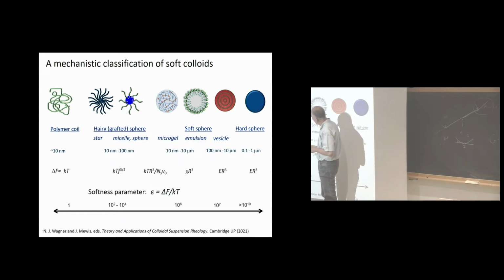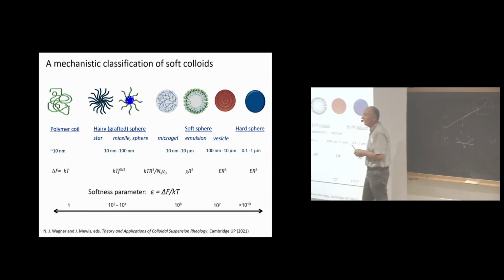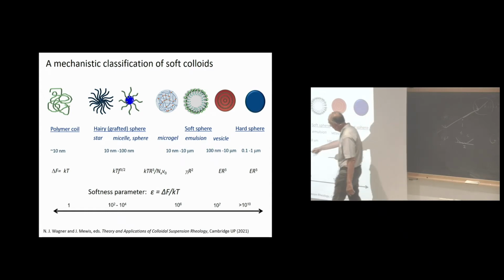If I go to the microgels, what is important here is the cross-linking density, right? If my cross-linking density is infinite, then basically I form a hard sphere, right? And so the way I described it is by the number of monomers between two cross-links. This is the monomer volume, and that's the size of the particle. And then when I go to these grafted particles, the number of the grafted chains is important, and I use for simplicity stars simply because they are simpler, so the number of arms themselves is sufficient.